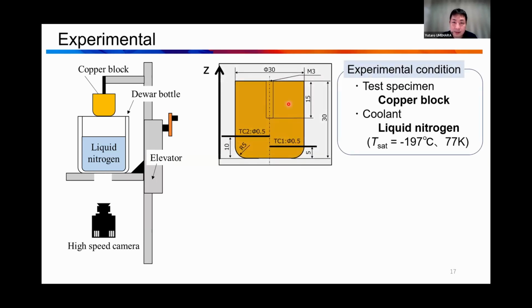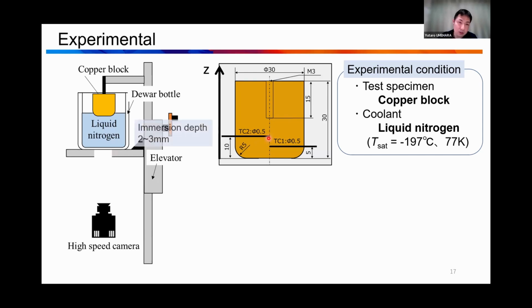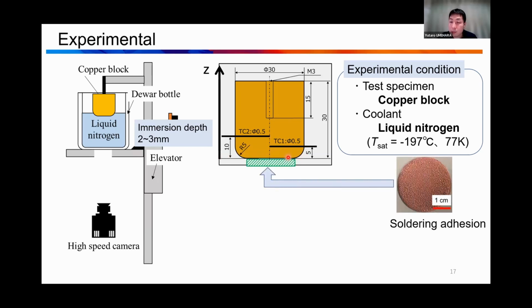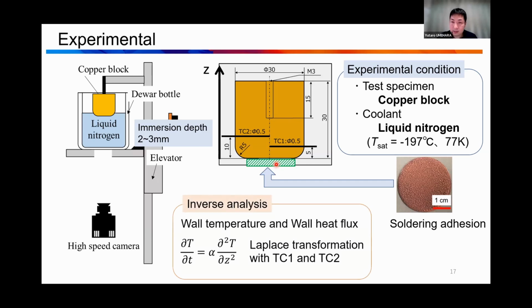So the schematic design is like this, and we inserted two thermocouples in the middle part, here and here. During the experiment, the immersion depth is 2 or 3 millimeters. We added the copper porous plate on the bottom surface using soldering adhesion. Then we calculate the boundary temperature and the boundary heat flux by using inverse analysis, with a Laplace transformation.